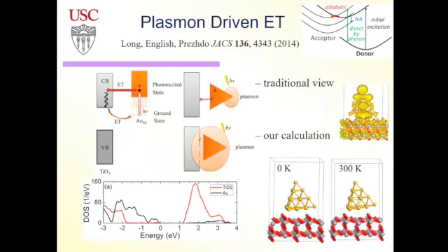Again, the same question: how can you do photochemistry or photovoltaics if everything should relax to the ground state in a metal? But people still try to make solar cells with metallic particles because they absorb light so well. The traditional mechanism is that you have this collective excitation of many electrons, a plasmon. Then there's Landau damping, or dephasing, where your collective excitation breaks into independent electron-hole excitations, and then charges can inject. But if you have electrons and holes, they should relax by vibrations, and energy goes to heat.